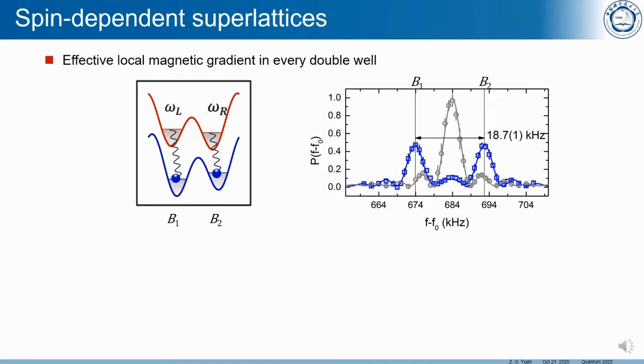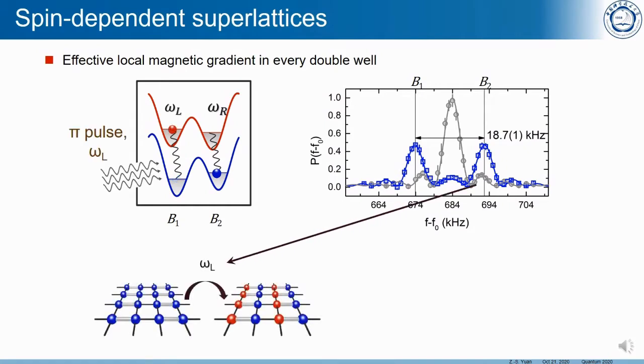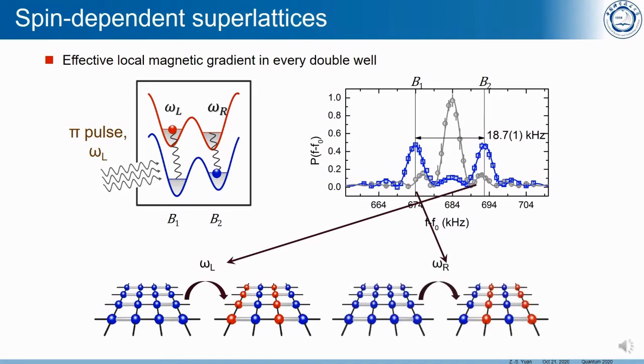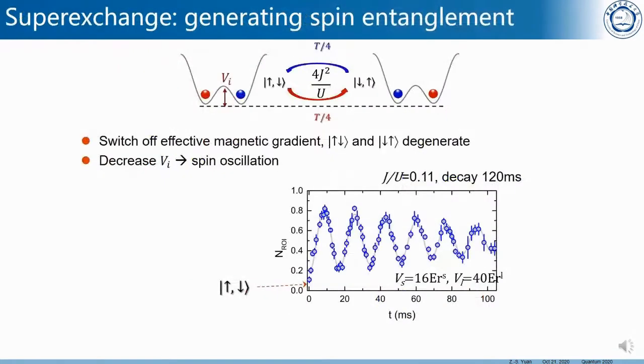The spin-dependent superlattice has a local magnetic gradient in every double well. Therefore, we can apply a microwave pulse with a proper frequency to selectively flip the right or the left atom on demand. And along the x direction, we create the initial state.